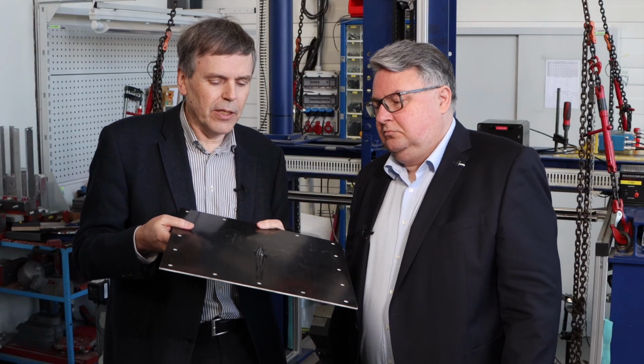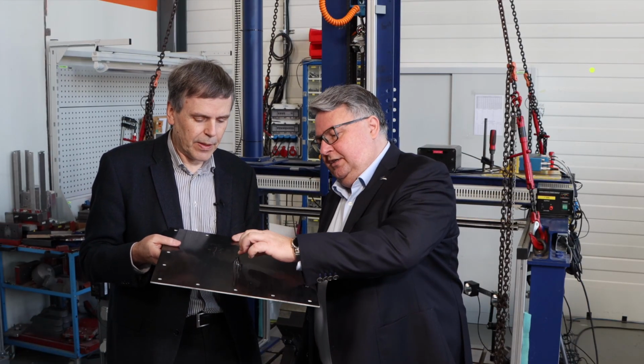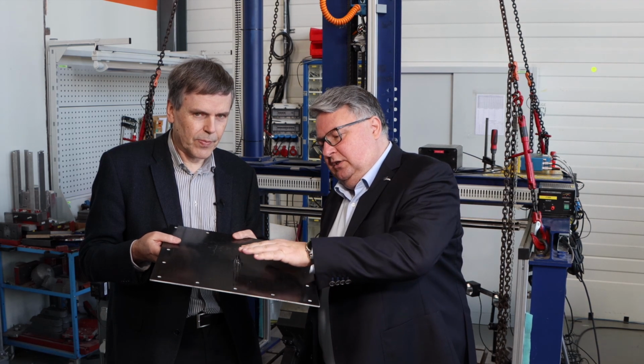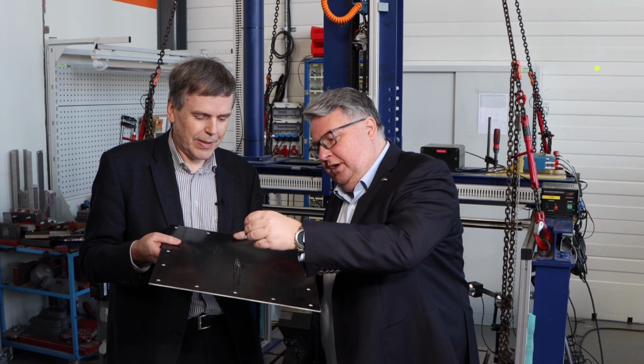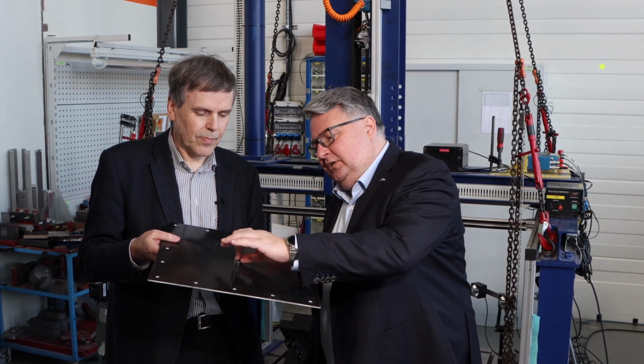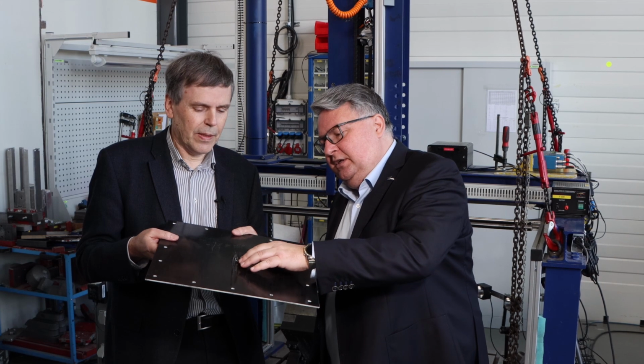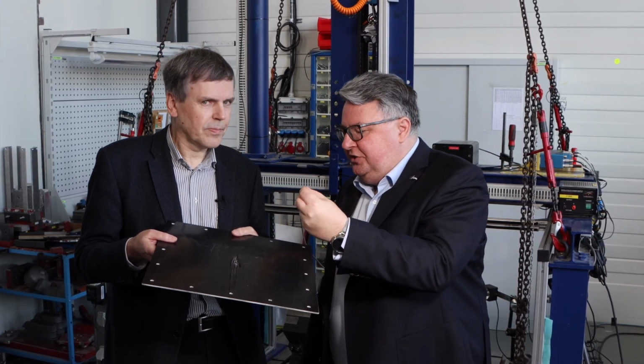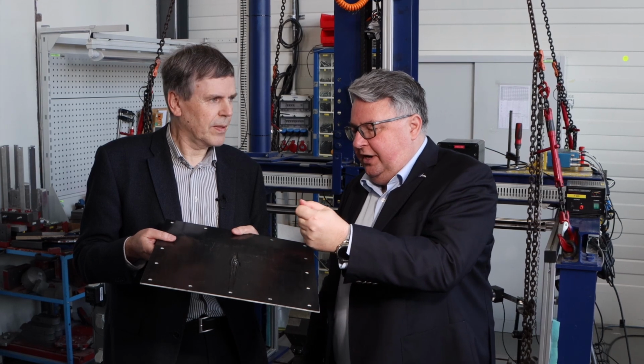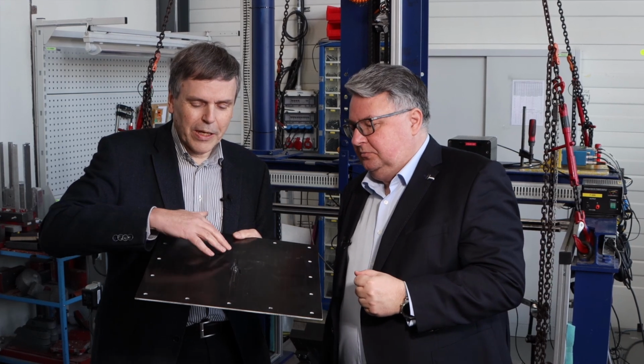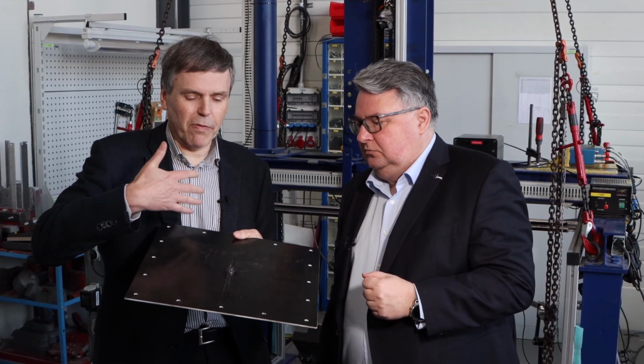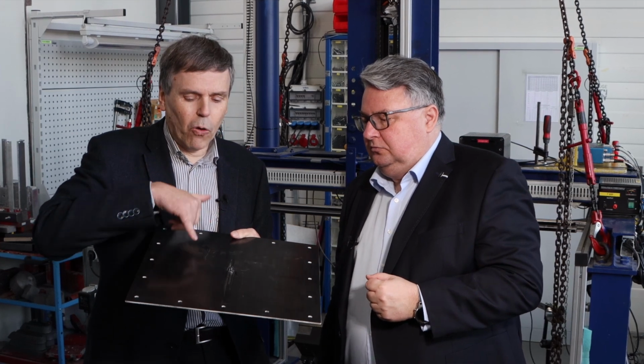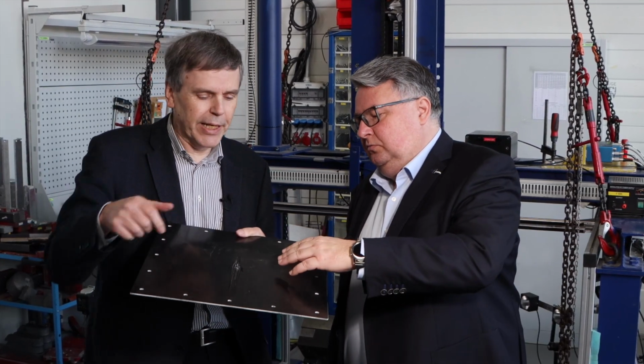This is a protection plate. There is still some space until the bottom of the battery box. So this would be a quite nice result. I'm seeing that some of the fibers, the carbon fiber, actually now I have one here, is really intact. The fiber, the roving, the tow is still there. That means there is some emergency running behavior. It's not disintegrating. It still keeps everything together. This is good news. Now of course the carbon fibers, but also the glass fibers, have a very high strength. And that's how it also dissipates energy by spreading the load.